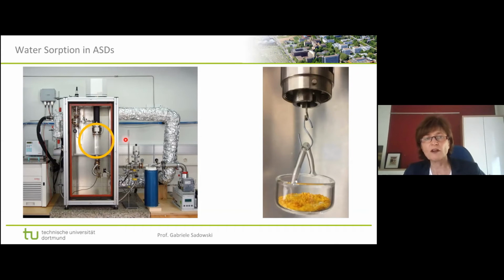So there is no door at the moment. Usually, of course, there's a door, but now we can see the inside. So the whole vessel here is at a certain temperature. And then we have a vapor tank outside where we produce water vapor, and this then enters the cell, and then we can have a very defined partial pressure of water in the system. So we can adjust very nicely the relative humidity in the system. And if water is absorbed in a sample, it gets heavier. That is quite simple.